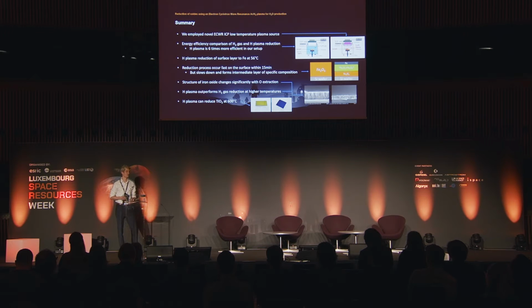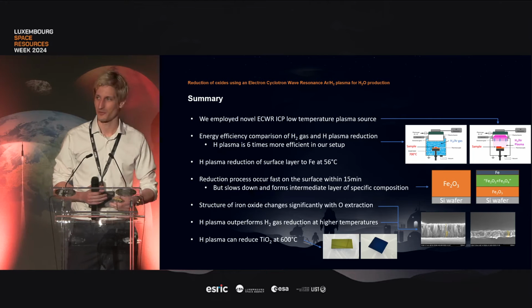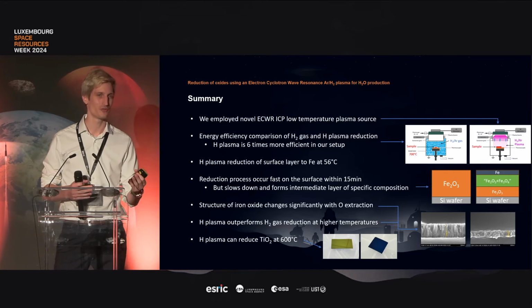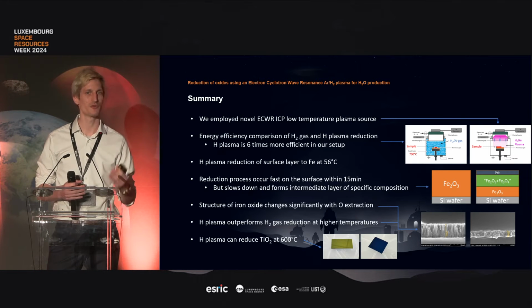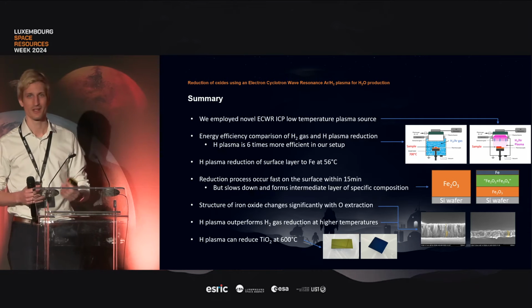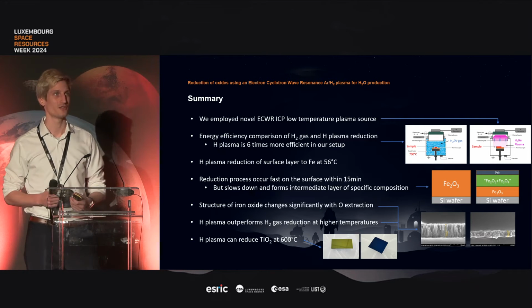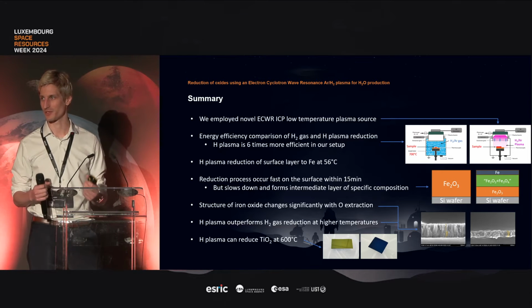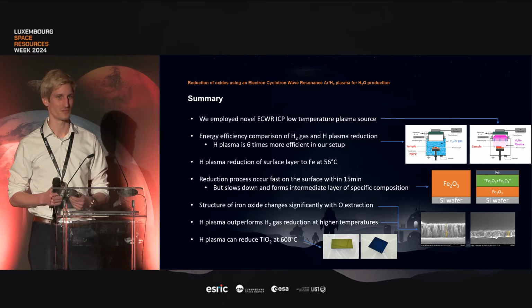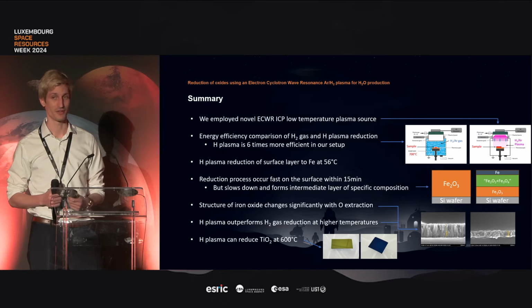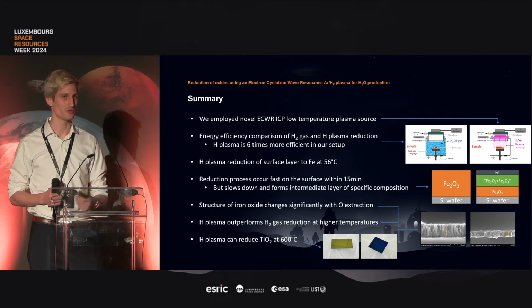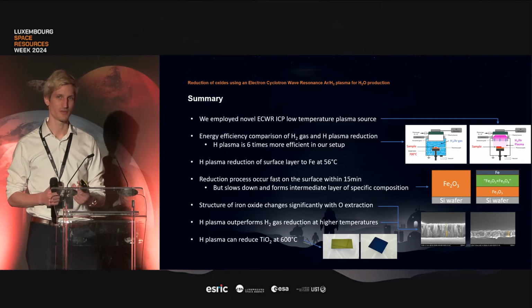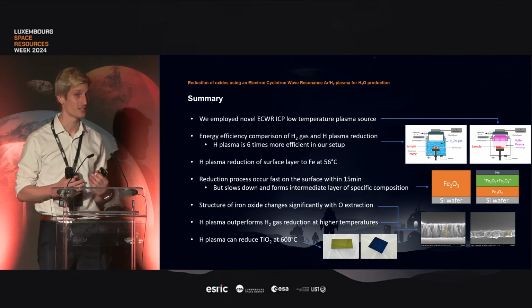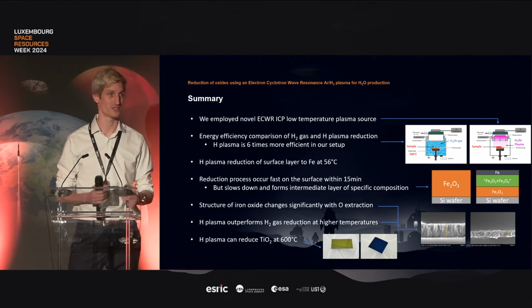With that, I will just shortly conclude what we saw. In this presentation, we wanted to improve the hydrogen reduction process. We proposed plasma. In our case, we proposed the low temperature novel type of source to perform its job. And we measured the energy efficiency between these two processes preliminarily, and we concluded that the plasma is more energetically efficient. We saw that we have a formation of metallic iron at a very low temperature of 56 degrees. And then we also observed a very specific intermediate layer forming, which can give us an indication of the mechanism of the process as well.